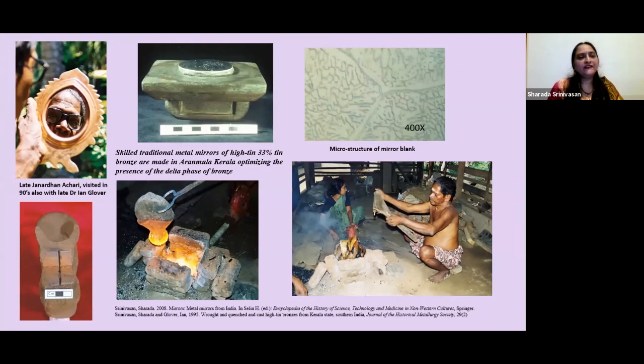And you're looking there at a very beautiful reflection of the late Janardhan Achari, who was one of the senior master craftspeople. Now what is happening here is that this intermetallic compound, which is a delta phase of 32.6% tin, is actually very reflective and very hard. It's very silvery colored. So by optimizing it, you get a very good material for a mirror. And then that was polished a lot and you get this beautiful mirror surface.